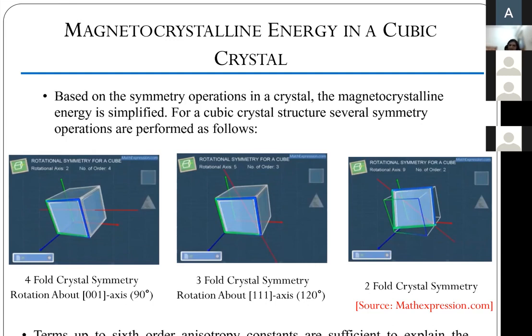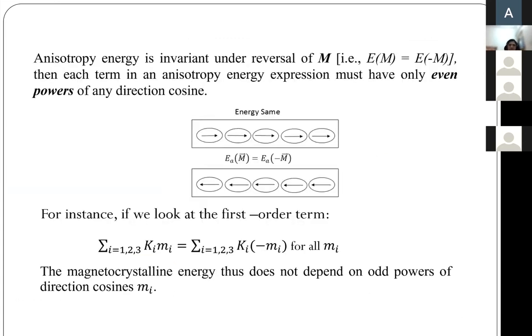So these 3 symmetry operations are corresponding to a cubic crystal. And where do we go? Yeah, so before we even go into a cubic crystal, one thing that is well known to us is that the energy has to be invariant under reversal of magnetization. So plus m, minus m should not matter to the energy, right? When we do that, all the odd powers will drop out automatically. So the magnetocrystalline energy can only have even powers of the direction cosines mi. Okay, so this one argument gets rid of half of the terms.